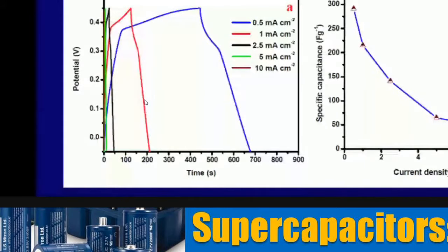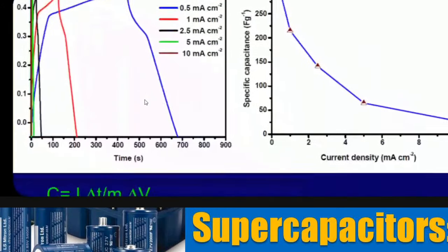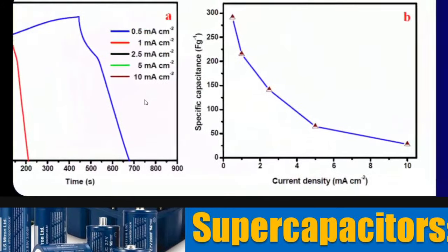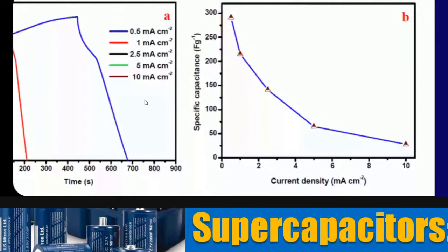the time decreases. Again, when you look at the current rate of charging and the specific capacitance, there is a decreasing trend. The explanation is the same. The material is not able to respond at that faster rate. And that is the reason why people keep on looking at materials where this decreasing trend can be arrested or at least reduced.